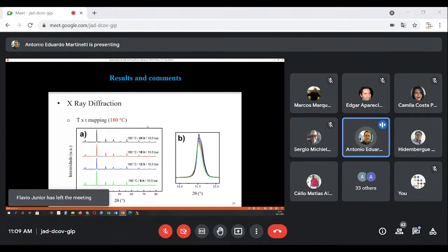So mapping the temperature versus time, starting at 6 hours, 180 degrees, the temperature was fixed at 180 degrees, same pressure, just to see the effect of the increasing time for the same temperature. We see a very, very small shift of the main peak of barium titanate, but we don't see the formation of any other phase.